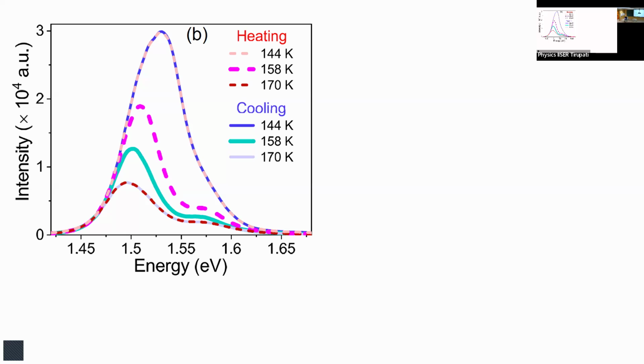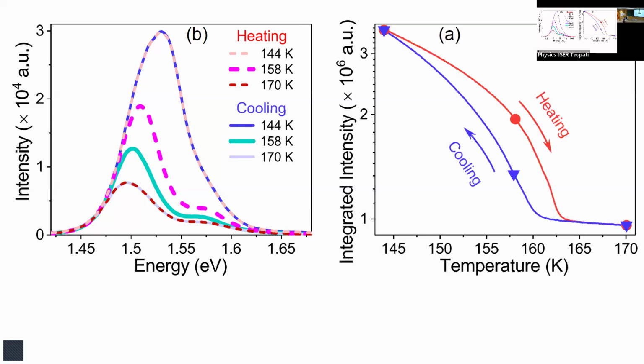You see that when I cycle through 144 heating or cooling, they're exactly on top of each other. The two spectra are exactly at the same place, because it's below the hysteresis of the phase transition. If I look at 170 Kelvin, which is above, these two are also exactly on top of each other. But when I'm inside the hysteretic region, 158 Kelvin, you see the two spectra depend very drastically on whether I came heating or cooling. I can just take the area, and if I plot, you see clearly the hysteresis of the phase transition. So this point and that point are different. That is saying these two are different. At this point they're the same, at that point they're the same.